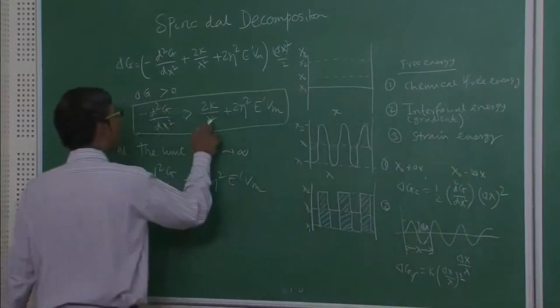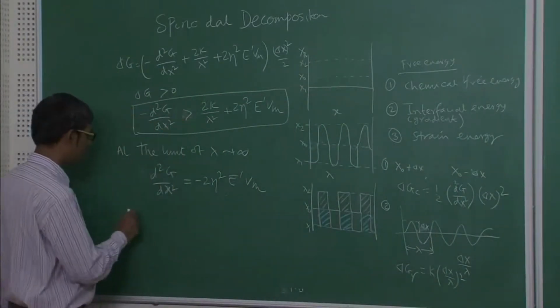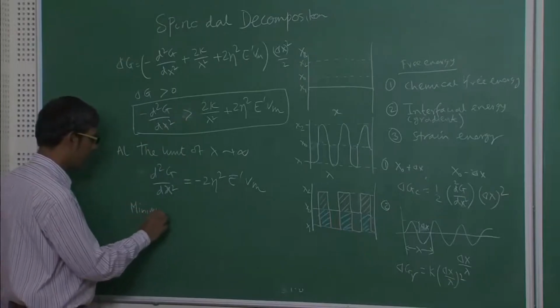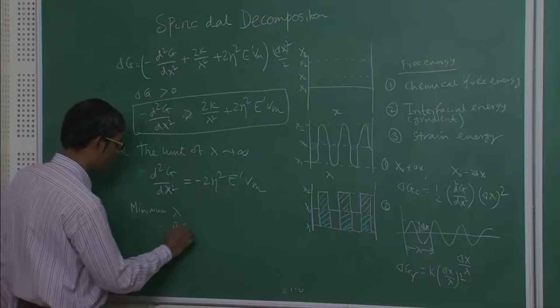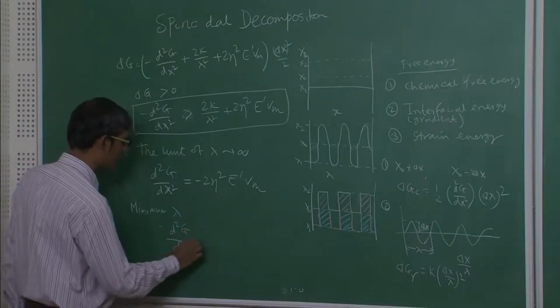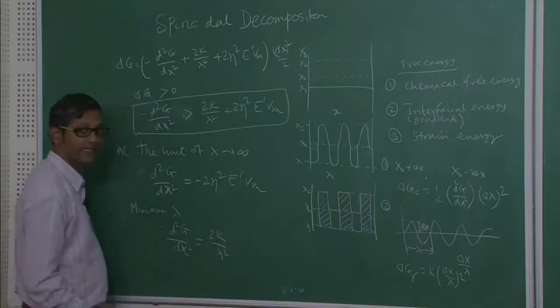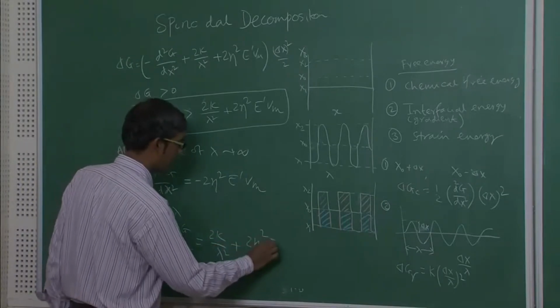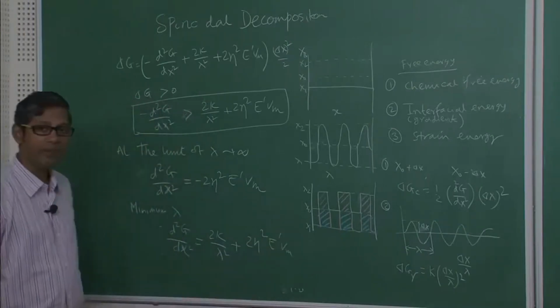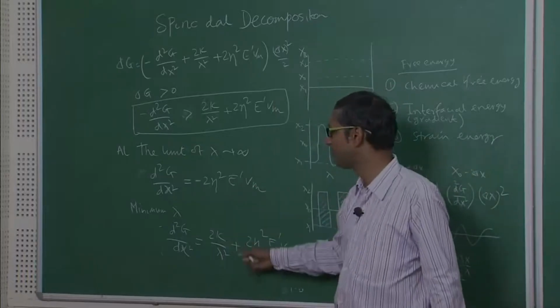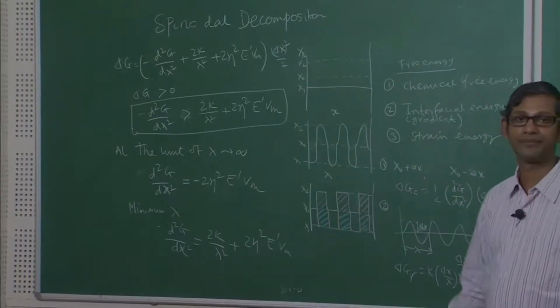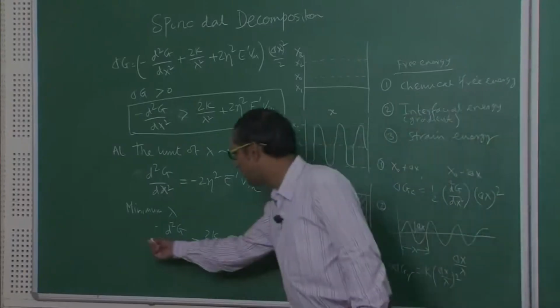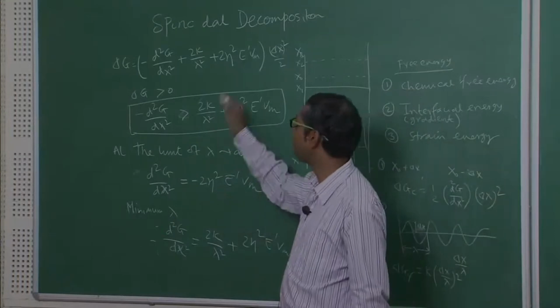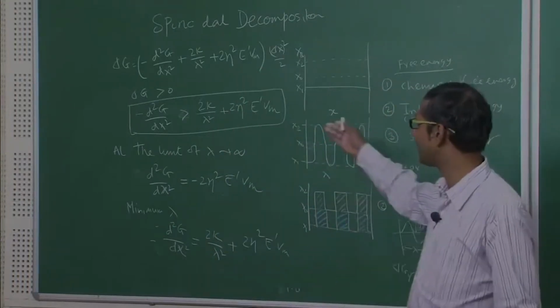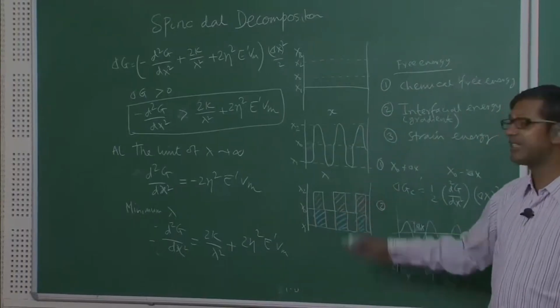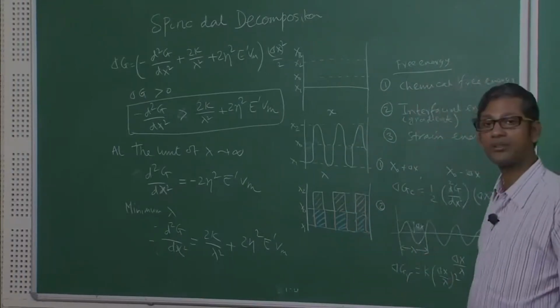Similarly, I can have minimum lambda when this is equal to 0. So minimum lambda will happen when all the chemical free energy part is consumed in creating gradient energy and strain energy. So lambda must be within these two ranges, maximum, minimum. It cannot be more than that or less than that. That is very clear. So once you consume the whole chemical free energy, you create a minimum lambda, and once you have very high lambda, there is no interfacial energy, obviously, because lambda becomes infinity, then 1 by lambda square becomes 0. So these are the two regimes of the compositional fluctuations possible, remember that.